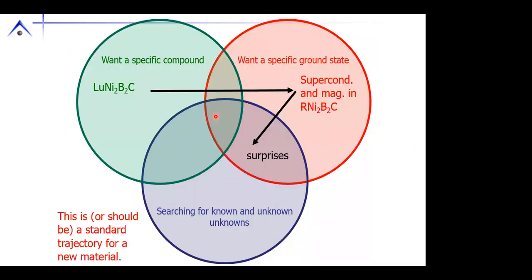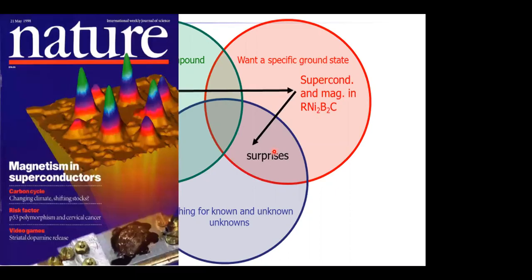Now, as we have a progression, we go from wanting a specific compound to wanting to study a specific ground state, the superconductivity and its interaction with antiferromagnetic order. But in many cases, you can have unknowns or surprises. And in the case of the boron carbides, the surprise was the fact that they were the first examples of a hexagonal to square flux line lattice transition due to non-local considerations. So as we increase the field, we could see the Abrikosov vortex lattice going from a hexagon to a beautiful square.